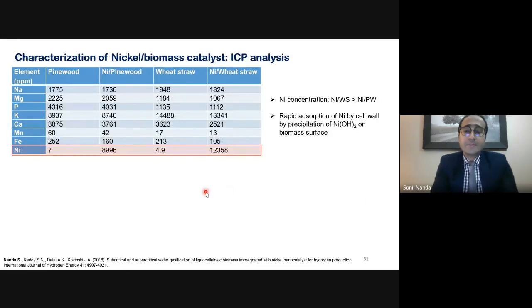Now we did an ICP analysis, inductively coupled plasma analysis, of the pine wood and wheat straw, because these are the two feedstocks that were taken. This is a control feedstock where it was just water mixed for 72 hours, no nickel nitrate, and here is the nickel nitrate hexahydrate solution with pine wood and wheat straw mixed together for 72 hours. As you can see here, where we added nickel, both pine wood and wheat straw were able to absorb the nickel through their cell wall.